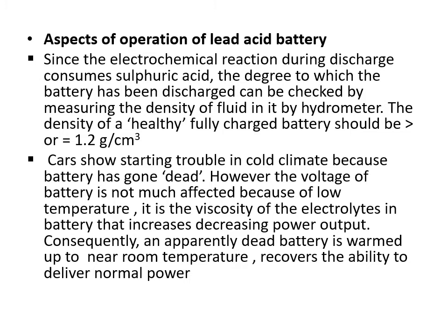Aspects of operation of lead acid battery. Since the electrochemical reaction during discharge consumes sulfuric acid, the degree to which the battery has been discharged can be checked by measuring the density of the fluid in it by hydrometer. The density of a healthy fully charged battery should be greater than or equal to 1.2 gram per cm cube.